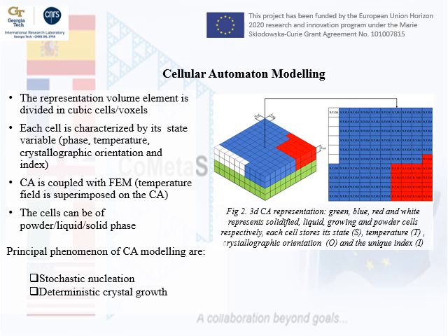There are two different physical mechanisms that are going to affect the development of the microstructure during solidification. The first one is nucleation. Nucleation is caused simply because when the temperature decreases after melting, there's a thermodynamic driving force for solidification, and certain parts of the representative volume element, so grains, are going to start appearing. So crystals start crystallizing, nucleating, and then if there is a high temperature gradient, so a driving force for solidification, these crystals can also grow.